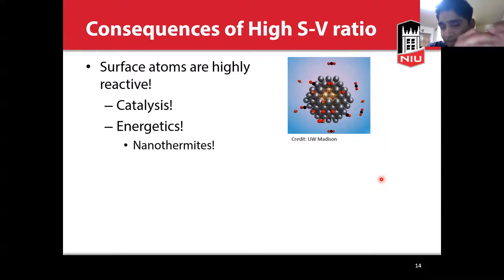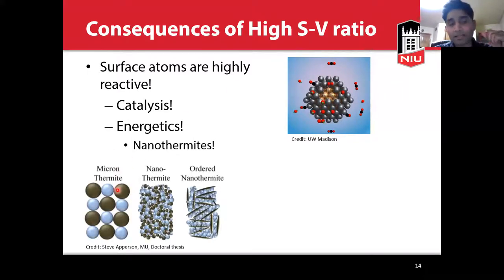But when I make the same material in the nanoscale, a thermite is nothing but a mixture of an oxidizer and a fuel. So if I have an oxidizer and a fuel, for example, copper oxide and aluminum, and I make them in the nanoscale, I mix them so that they are nicely homogeneously mixed, I make what is called a nanothermite material. Okay. This is what I mean. So that's a micron thermite that you would find in your fireworks. And when I make this as a nanothermite and when I ignite them, the rate of reaction is much higher because again, the surface atoms are very reactive. The volume is so small, the rate at which the reaction propagates is going to be extremely high. So you can actually compare the rate of energy release to that of typical explosive materials like TNT, for example.